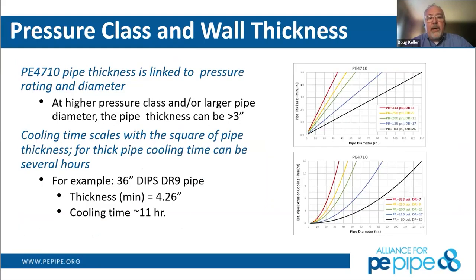So why do we need low sag material? Well, if you're familiar with the way we pressure class polyethylene, for example, a DR11 is a continuous operating pressure of 200 PSI. And that DR is the average outer diameter of the pipe divided by the minimum wall thickness. So as long as that ratio is an 11 and you're running in a water environment at room temperature, your pressure class or your pressure rating for the material is 200 PSI, continuous operating pressure.